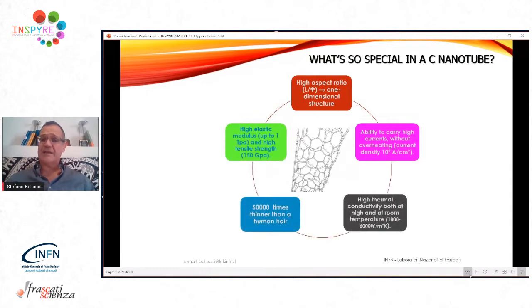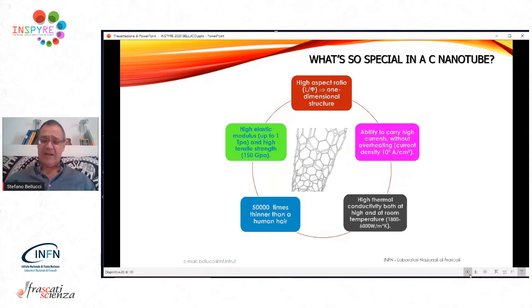What's so special in a carbon nanotube? A carbon nanotube has a very high aspect ratio. That means it's a quasi-unidimensional structure. It has terrific mechanical properties. In terms of elasticity, its Young modulus, or elastic modulus, is about 1 terapascal, which means orders of magnitude higher than special steels, for instance. It has the ability to carry very high density of current. That means it can replace copper, which we normally use for the transport of current. This can reach up to 10 to the 9 ampere per square centimeter. And finally, it has very, very high thermal conductivity. That means that its thermal properties are suitable, for instance, for space applications in re-entry vehicles that need to realize shields that can sustain the very high temperatures in the re-entry in the atmosphere.